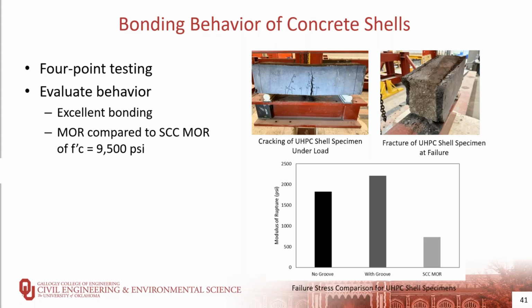The bonding was excellent as we could not see any significant separation between the UHPC and the SCC, even after we completely failed the specimens to see the cross-section, regardless of the interface, whether it was grooved or smooth. In terms of modulus of rupture, both trial specimens exceeded the SCC modulus of rupture. You can see from the figure on the bottom here that the measured MOR from both specimens was more than double the calculated MOR for the SCC.